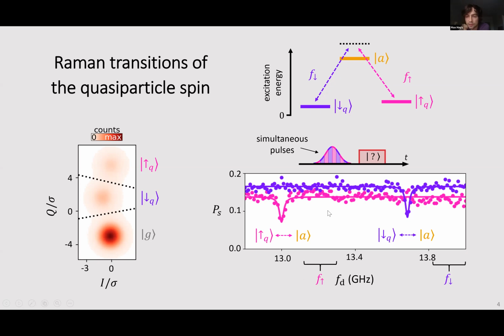But there's actually another problem we have to solve before we can move on to Raman transitions. If you look at the background in this plot, you can see that when we're not driving any transitions, the two spin states have roughly equal probability. So even if we were to drive a Raman process between the two spin states, because this isn't directional, it induces a rate from up to down at the same rate that it goes from down to up, we wouldn't see any population transfer, or we'd see very small population transfer anyway, and it'd be difficult to detect.